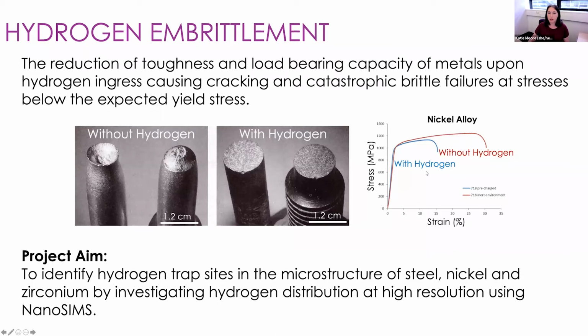So if we look at this graph over here, we can see a stress strain curve. When we look at this nickel alloy being tested without hydrogen, it fails here. But as soon as you've got hydrogen introduced, it fails much earlier. And you'll see in these images here, it also fails with a brittle fracture surface as opposed to the expected ductile fracture surface.